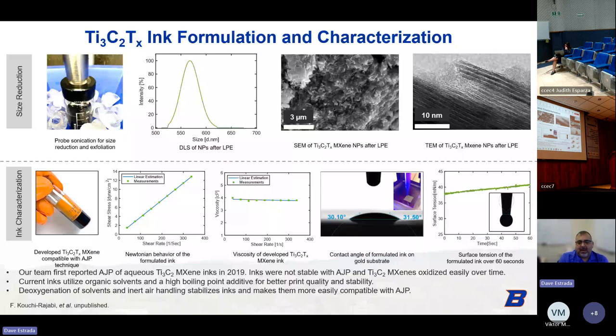And so to do that, we do that through probe tip sonication. You can see that photo here, where the probe tip sonicating horn actually goes through a PDMS membrane and into the solution of MXenes. And this is all sealed under an argon environment. So we're really trying to minimize the oxidation of the titanium layer, which can become more reactive at the nanoscale.